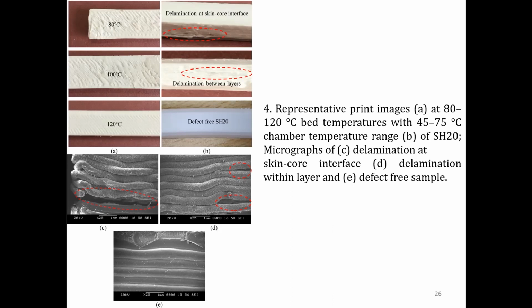So if you look at Figure 4, part A, which can be seen here, I'm going to talk a little bit about this now. These are the representative print images after peeling the samples. Peeling meaning removing the samples from the substrate at different bed and chamber temperatures. The improper adhesion results in non-uniform surface texture. In case of 80 degrees, when you set the bed temperature as 80 degrees, and the chamber temperature between 45 to 75 degrees. Now, if you increase the bed temperature to 100 degrees C, improper raster diffusion at the base layer forms a very rough surface, and there are some void formation possibilities.